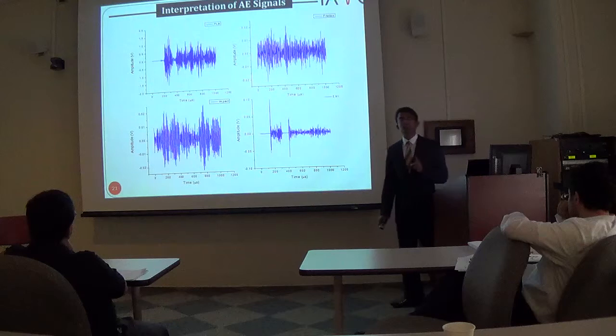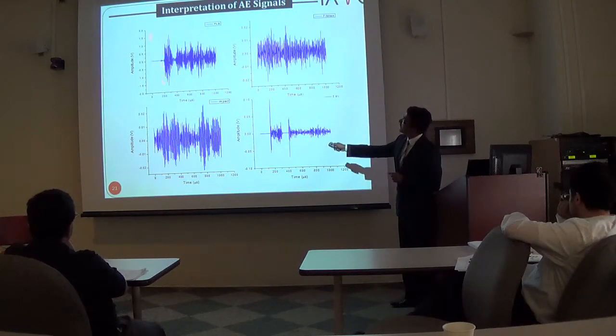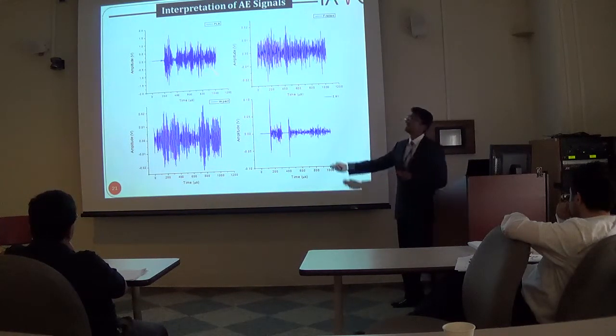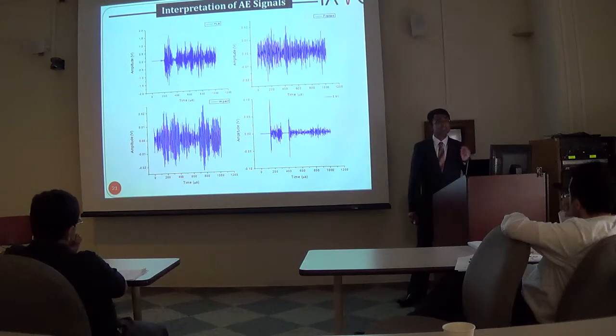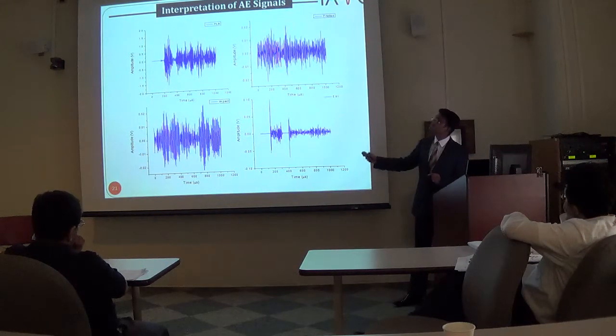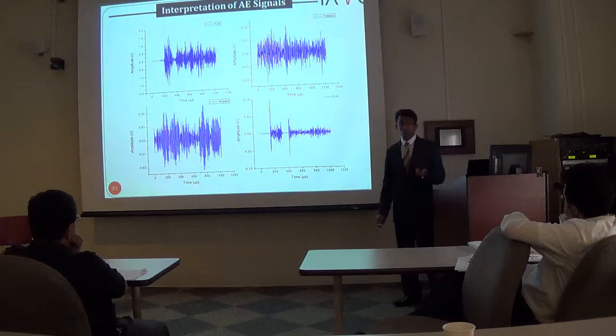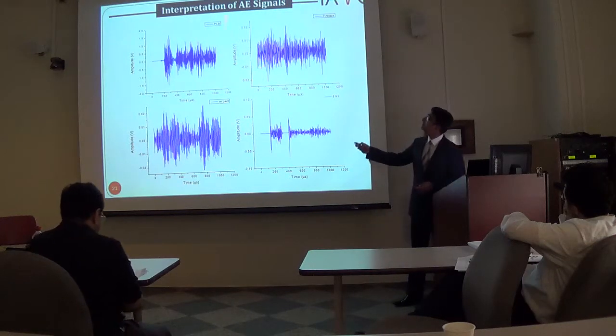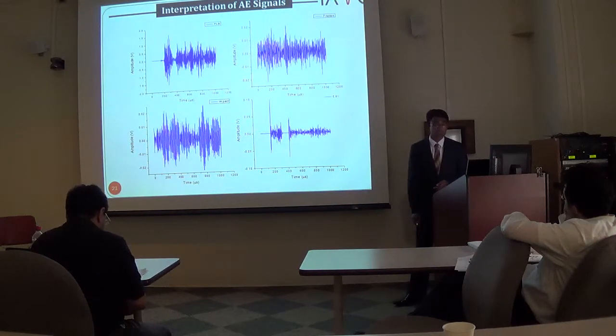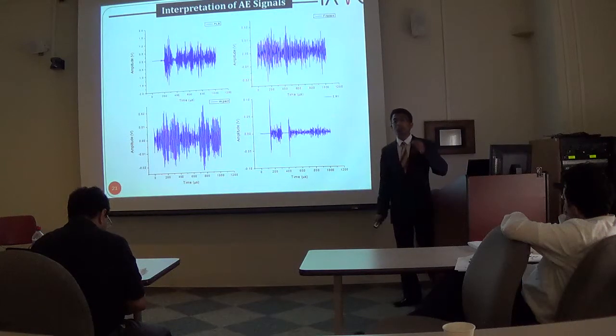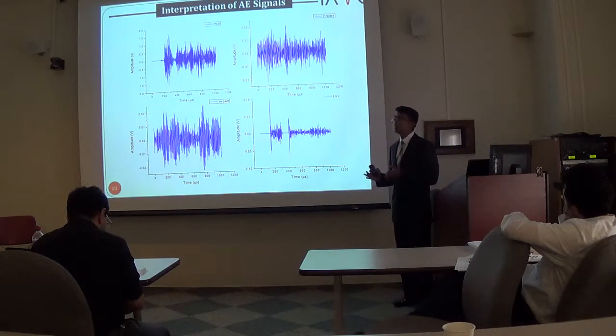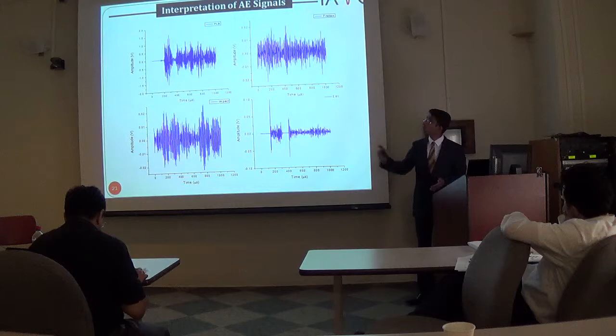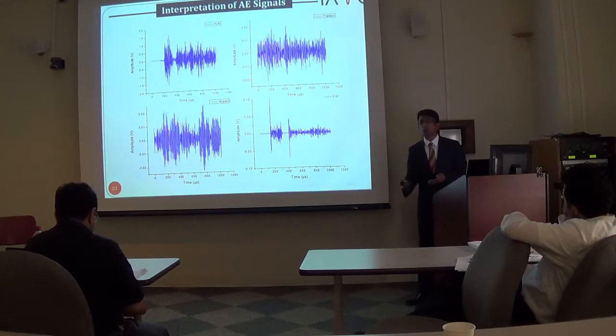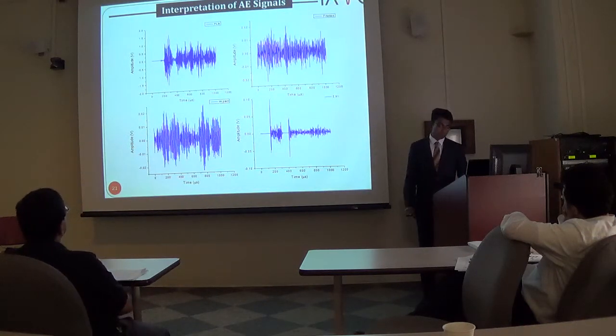Now, another thing to be noted here is the pre-trigger activity. It can be clearly seen that signals that have a burst type emission have very little pre-trigger activity, while signals that produce continuous type emissions, such as noise and other secondary sources, have significant pre-trigger activity associated with them. Thus, it is essential to have a valid pre-trigger activity in order to separate and provide an insight into the potential source mechanisms of the material.